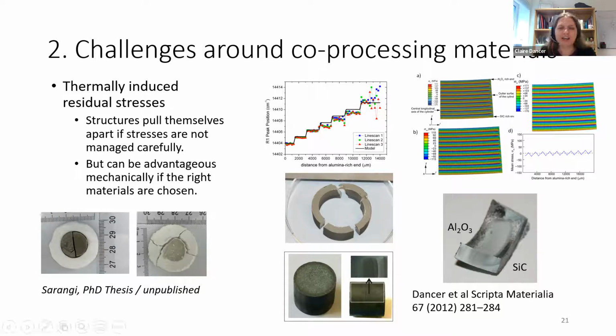So I had to go and raid my rather depressing folder of broken ceramic pieces from a project I did where it was basically breaking everything every time. This is a ring of material, and this is a piece of it. It consists of aluminium oxide at one end and silicon carbide at the other. The difference in expansion coefficient between those two materials is pretty much double, so the material tries to pull itself apart. I went through 6 months of basically pulling broken pieces of material out of the furnace.